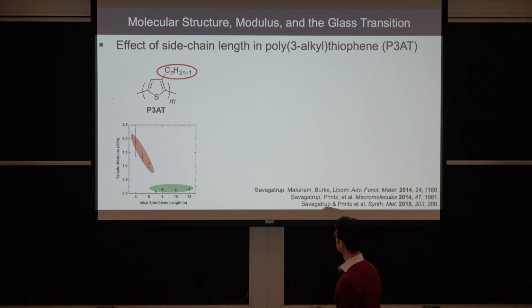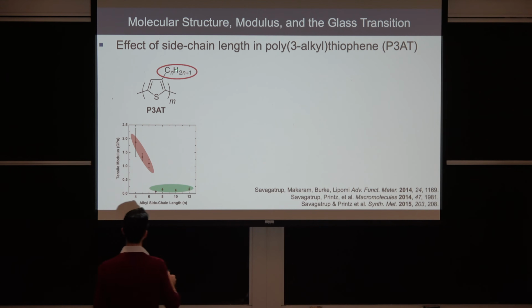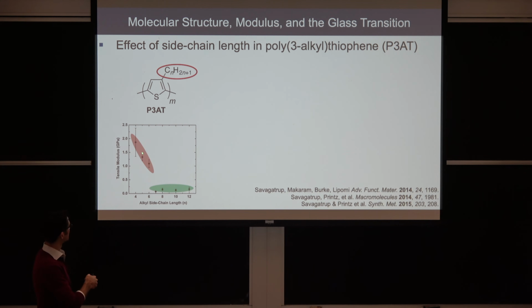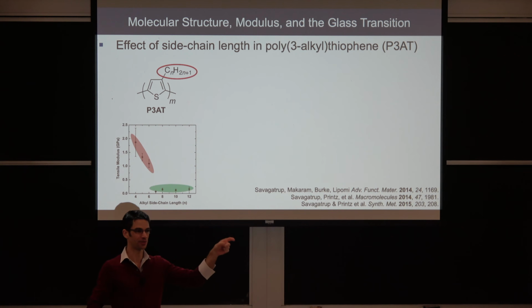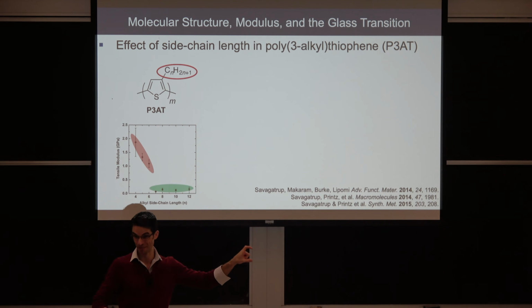And as you increase the length of the side chain, so as you increase n, and we plot the tensile modulus versus the side chain length, we have this steep drop off between C6 and C7. Now is that something magical about C7, about 7 carbons long? Not necessarily. It's really where we have the thermostat set in the lab.